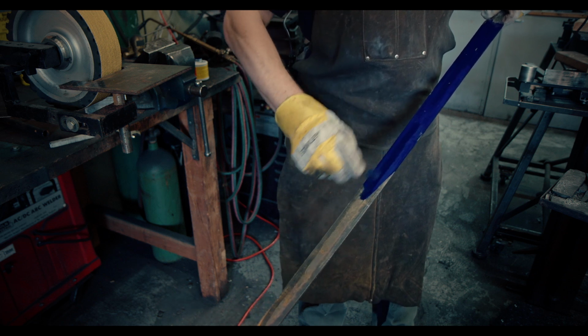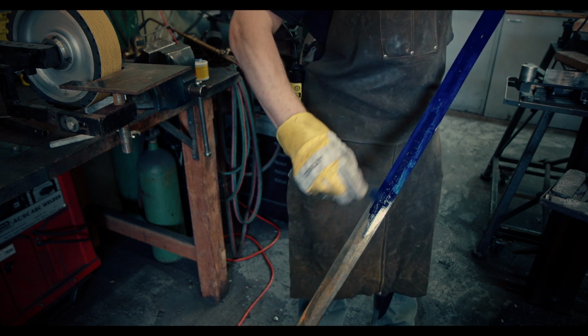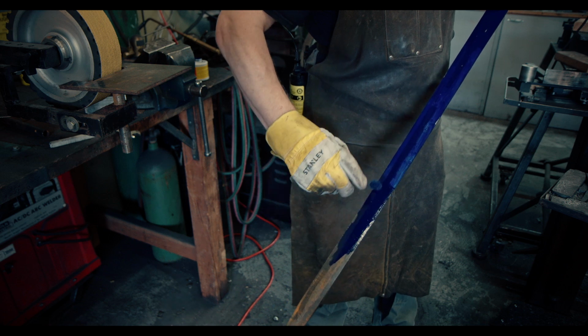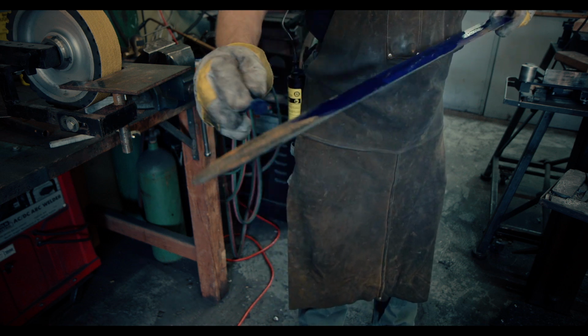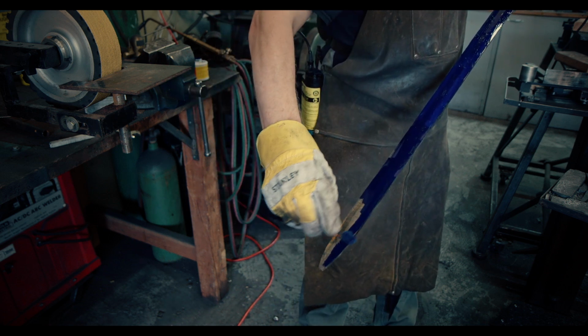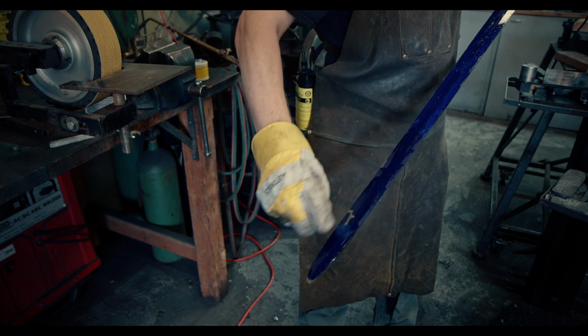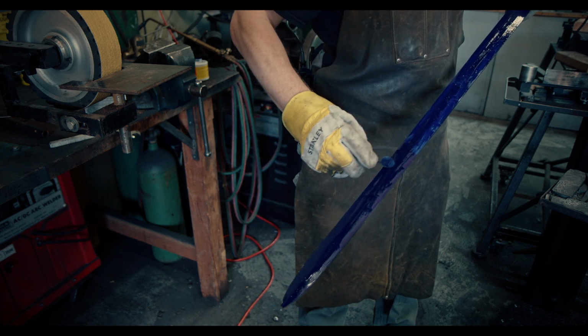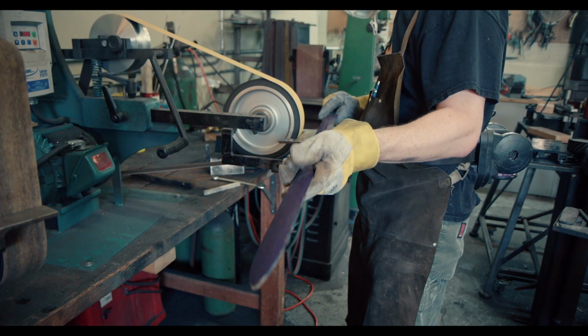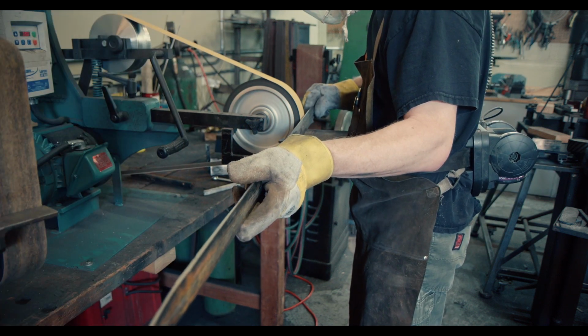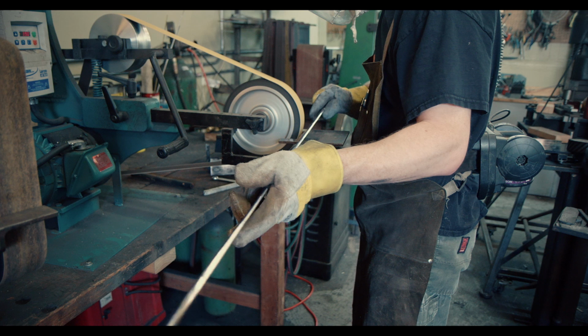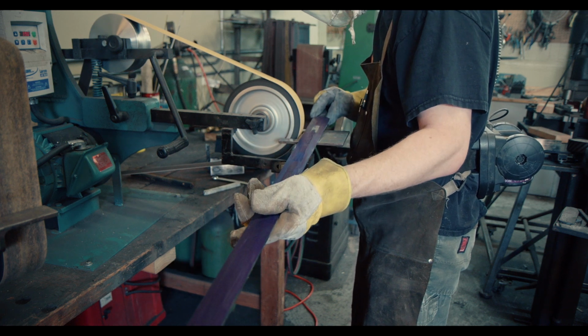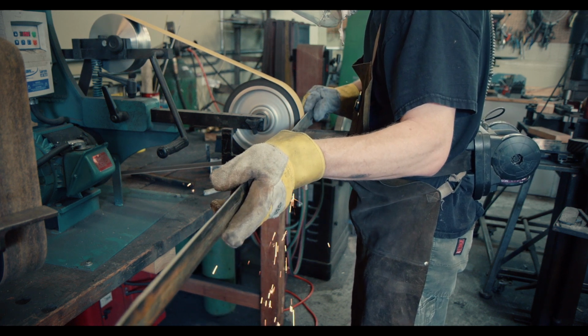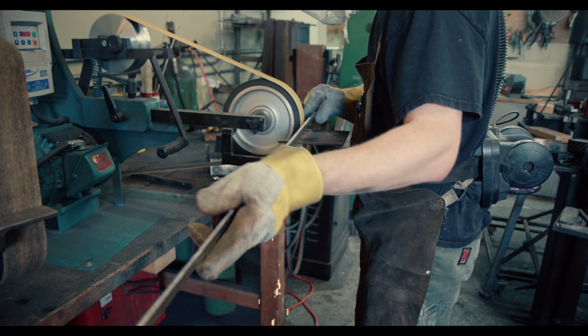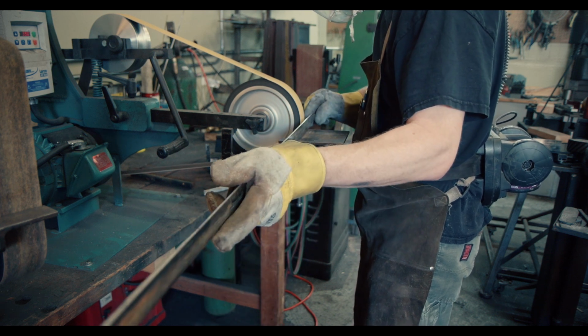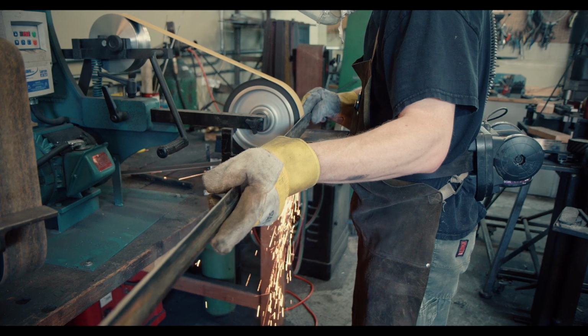This brings us back to symmetry. Every place in the sword that is not symmetrical creates an opportunity for unequal stress and thus warping and bending of the sword when quenching. I'm getting ahead of myself though. In the previous episode I was done with all my forging work. However, before the sword can be heat treated, its final geometry needs to be created. That means the sword has a well-defined and symmetrical cutting edge, as well as a fuller in the middle to reduce its weight.